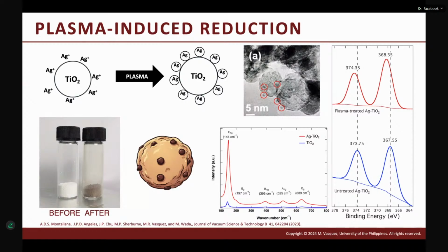In order to improve or shift the activity of TiO2 to the visible region, usually you couple it with noble metals such as silver. So here we have silver. In our process, we put the TiO2 in silver nitrate, and the silver ions will go to the TiO2, but they are still in ion form. So we treat this with plasma to reduce Ag+ to metallic silver.